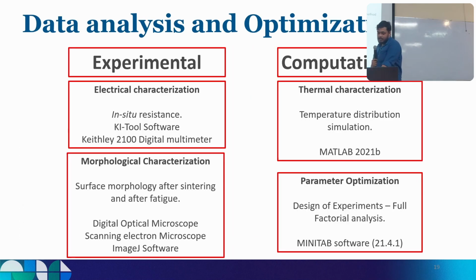Those data were analyzed using multiple methods, both experimental and computational. First, I did the electrical characterization using the resistance data collected from the digital multimeter and analyzed how the resistance changes. Crack formation was also analyzed using SEM images and digital microscope images. Some simulations were carried out to show whether the interconnect was completely sintered, and some statistical analysis was carried out to determine optimized laser parameters for sintering. We will discuss that in more detail.